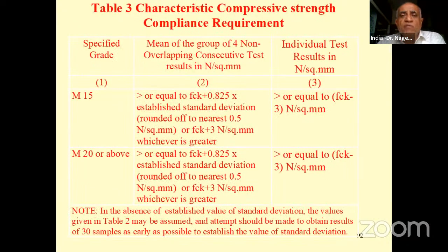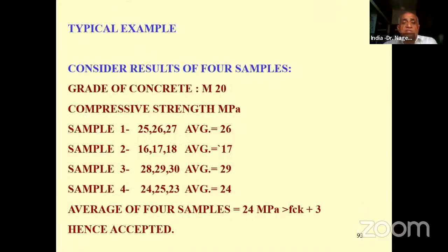Mean of the group of 4 non-overlapping consecutive test results for M20 and above grade of concrete shall be greater than FCK plus 3. There are some other things, let us not worry about it. FCK plus 3 is what we are looking for. Same thing is shown here. We are getting average of 4 samples as 24 MPa, which is greater than FCK plus 3, that is 20 plus 3, 23 MPa.